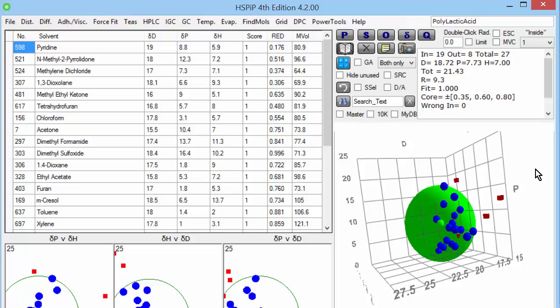You shake it in the test tube or you ultrasonicate it. You look at it after five minutes or half an hour or a day. And those good solvents where the dispersion is happy will look fully suspended and dispersed, whereas the unhappy ones will just be sitting skulking at the bottom.